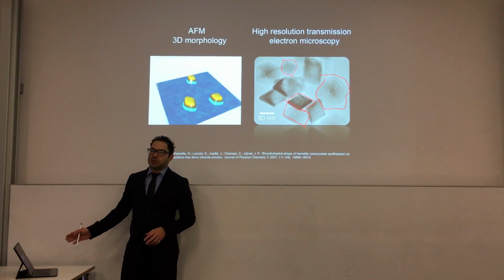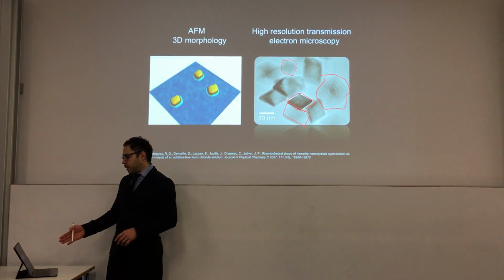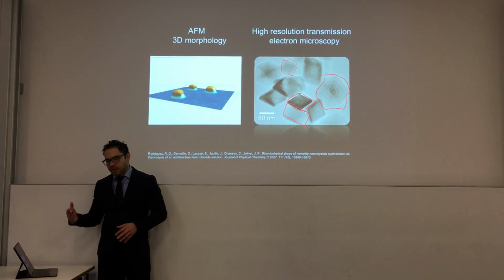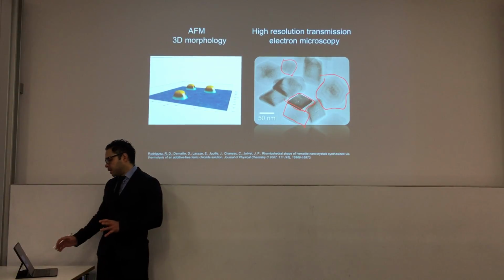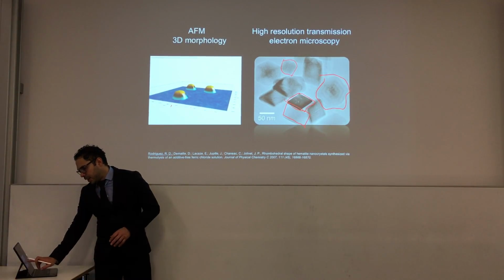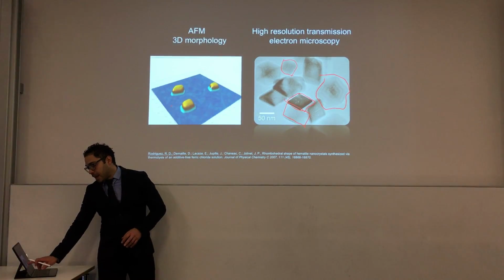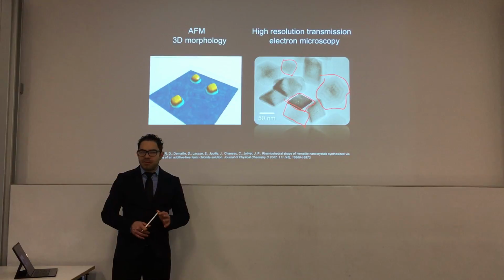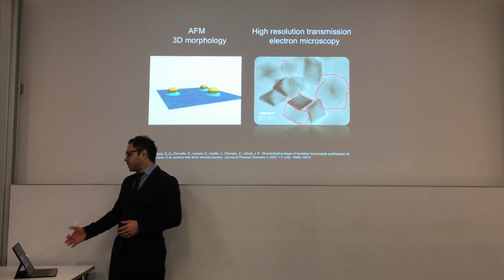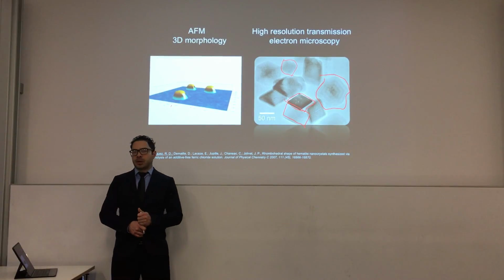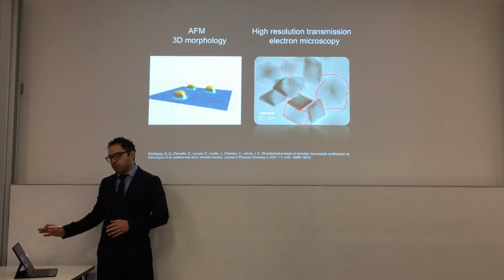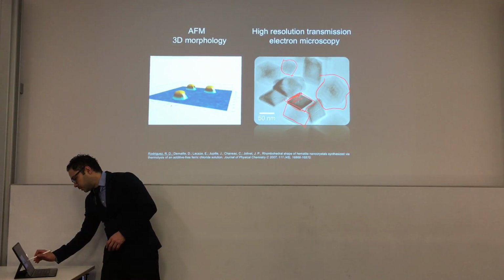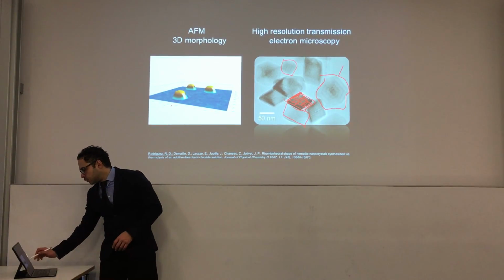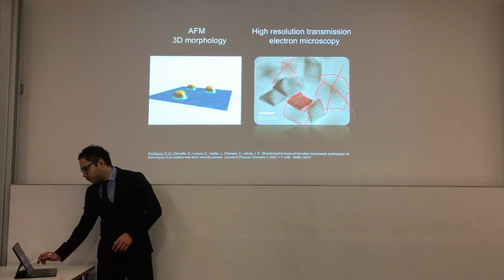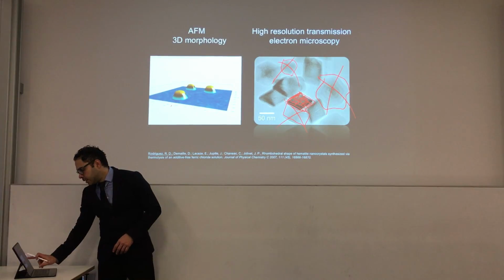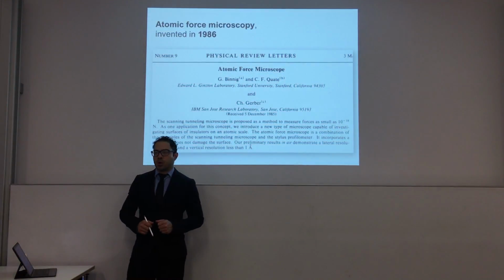If you have the same nanoparticle system visualized in atomic force microscopy, you will obtain the following images. You have this 3D information of your sample, and this is very important because, for example, here it allowed to end with something that was, until this moment, a conflict in the literature, something that was not very clear. What is the real morphology of this kind of nanoparticles? Atomic force microscopy allowed to determine that the actual morphology of the nanoparticle is more like this one that you see here. It's more like a lozenge. But there is no such thing as hexagonal nanoparticles or spherical nanoparticles or rectangular nanoparticles now. AFM shows that the only morphology that you have there is rhomboidal.